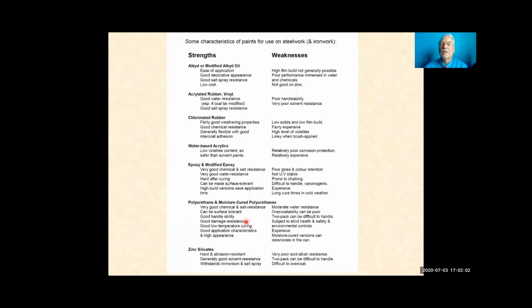I'm not going to go through those. They're there for you to just look at, because somebody asked what the best paint is. I have to tell you there is no best paint. Sorry, there are advantages and disadvantages of each one, and these are the advantages and disadvantages. The common paints are the alkyd oils, and that's a single pack coating for outdoor metalwork, or the epoxies, but they're not UV stable. So we use epoxies and then put the polyurethanes on the surface. So if I can just short circuit a very long potential lecture, for the cheaper applications, we tend to use the single coat epoxy, alkyd oils. For the more expensive and challenging environments, we tend to use a combination of the 2-pack epoxies and polyurethanes.